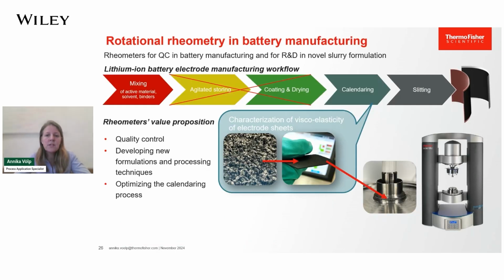In the subsequent section, we take a look onto characterization of the dried processed electrodes with rotational rheology. Rotational rheometers can not only be used as a QC tool to check wet slurry viscosities, but also to characterize the viscoelastic properties of dry electrode films. This dry processing is still subject to investigations because the calendering, homogeneous sheets, and scaling up is very challenging.